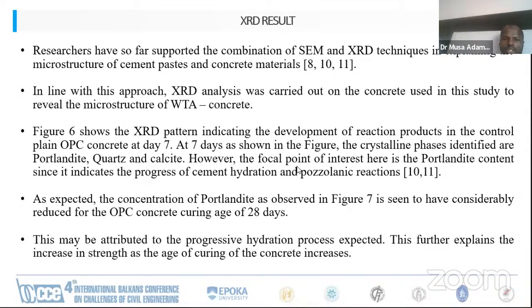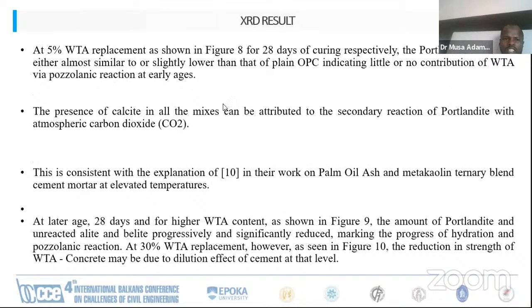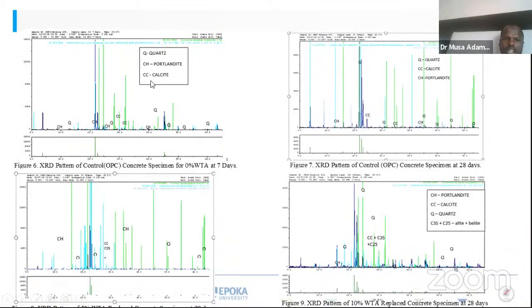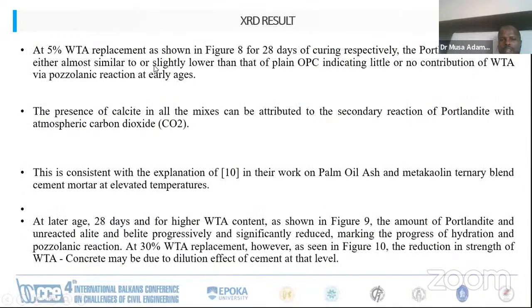So these are the figures. You can see the quartz, you can see the CH and the CC. These are all labeled. So at 5% WTA replacement, as shown in figure 8, for 28 days curing period, the portlandite content is either almost similar to or slightly lower than that of the plain OPC, indicating little or no contribution of WTA via pozzolanic reaction.